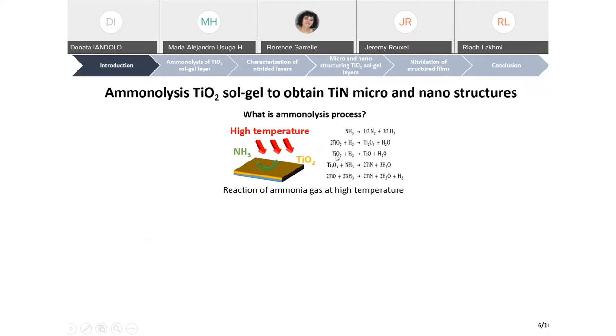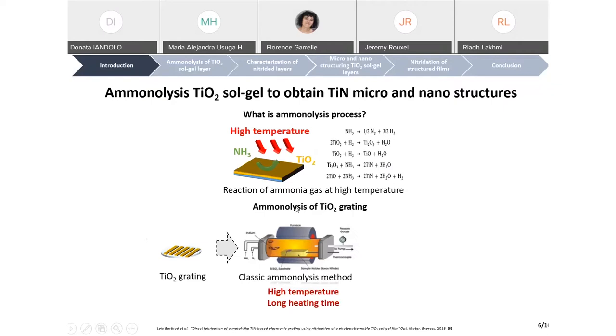It was demonstrated that it is possible to obtain titanium nitride grating using the ammonolysis process. Some authors have realized titanium dioxide grating using a sol gel. Using the classic ammonia method, we have obtained a titanium nitride grating conserving the same structure. The problem of the classic ammonolysis method is that it uses a high temperature and a long heating time.